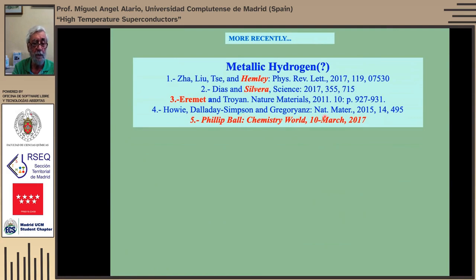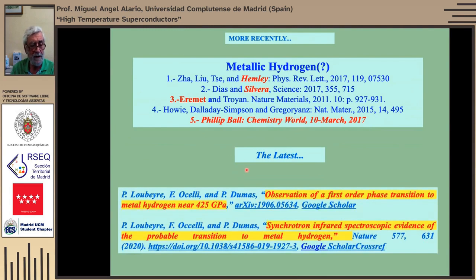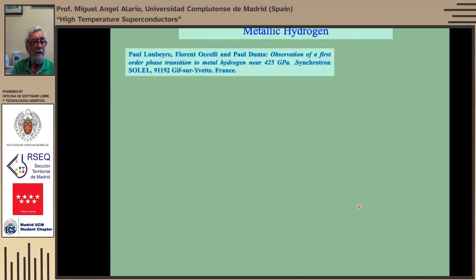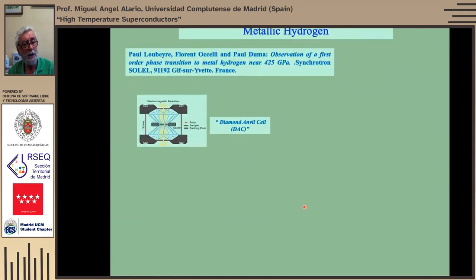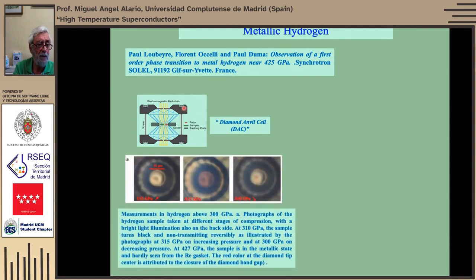This article by Philip Ball is very nice because it describes the good things about this, although there is not really clear evidence. But very, very recently, there is a group in France working at no less than 425 gigapascals, in a synchrotron, that has found probably metallic hydrogen. This is done in a diamond anvil cell. You have two diamonds here, and then you put in the hydrogen, something which is not very simple, and you make pressure by pressing these screws. You make the diamonds get together.